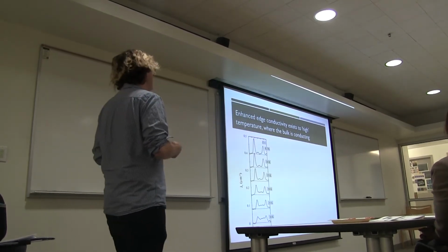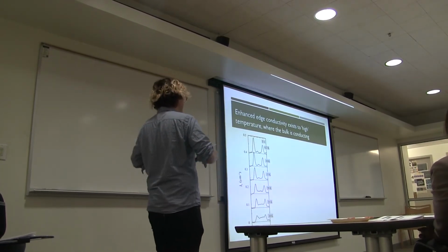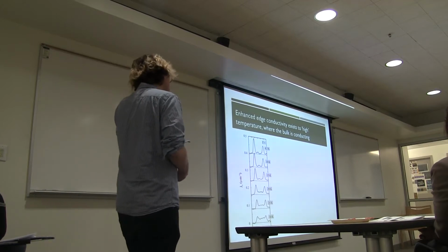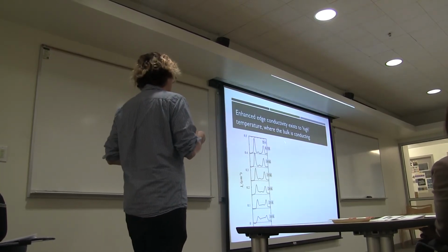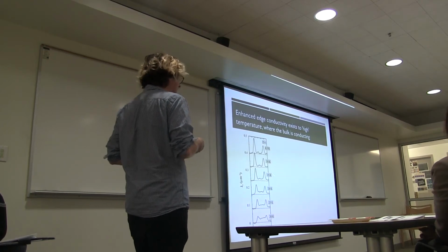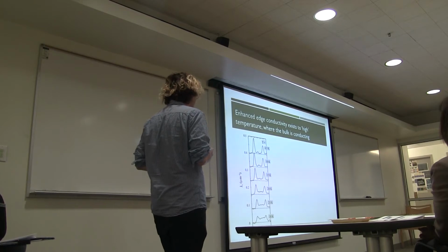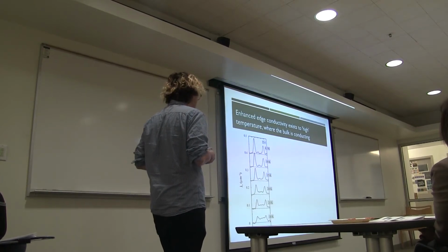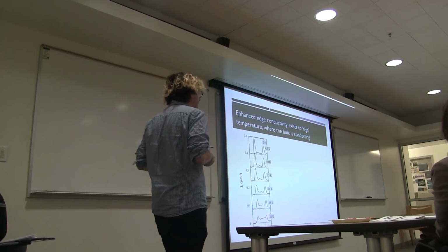So now we want to image the sample under a variety of conditions. I'm going to show you a couple of the things we did. At low temperatures, it looks like the line cut I just showed, but as we raise the temperature of the sample from 4 Kelvin to 30 Kelvin, the amount of current flowing in the bulk, in the middle here, rises as we increase temperature, and the amount of current flowing in the edges decreases.